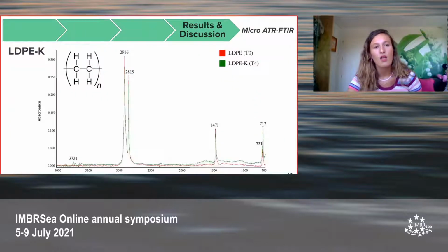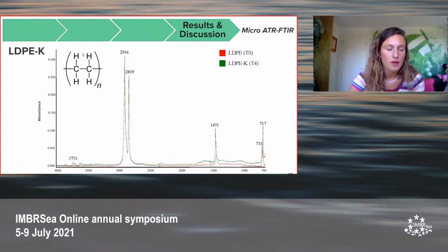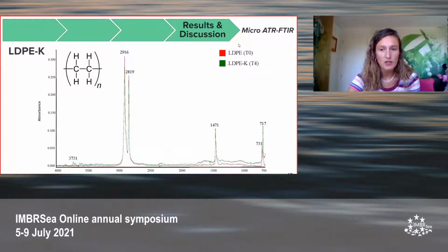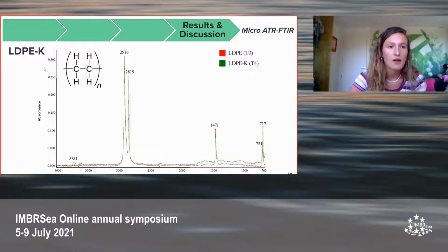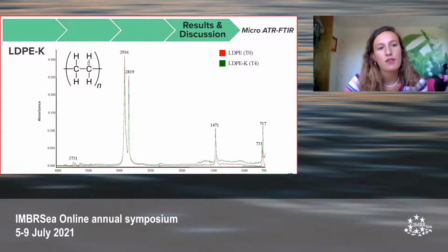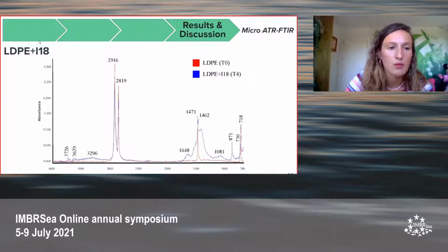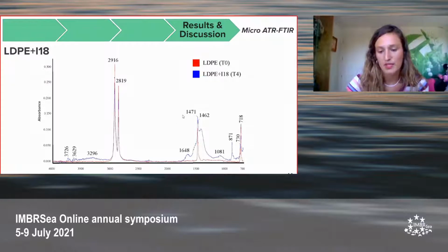plastic. Moving on to the FTIR, we compared the spectrum at initial time, before the experiment, and after the 45 days of incubation time, which is marked as T4, for both polymers, comparing the controls marked as K and the samples with inocula marked as I18. So in this case, for the low-density polyethylene controls, the spectrum does not change throughout time. However, when we move into the samples with the inocula, some changes are appreciated.